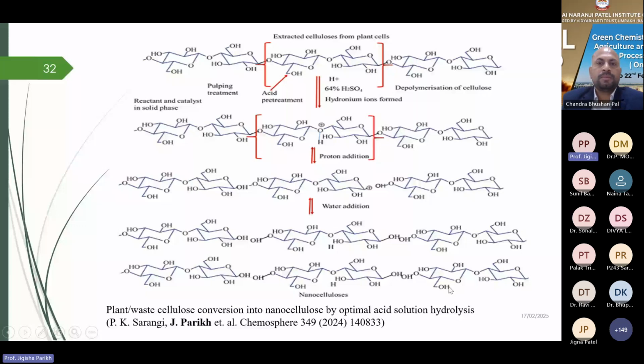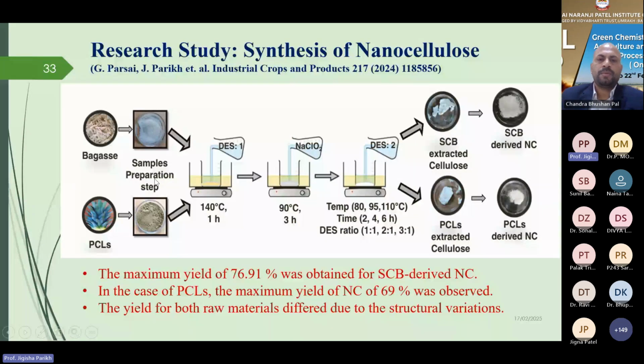Okay, so in terms of the methodology, as I said, we have used sugarcane bagasse and the pineapple crown leaves, which has been further feed prepared. So we have to convert into a uniform size before we utilize it under this typical process, and then we receive the cellulose extracted from it, depolymerize, and then convert this into nanocellulose, because here we have used the whole biomass. So we have to extract first the cellulose, and then cellulose is converted into the nanocellulose.